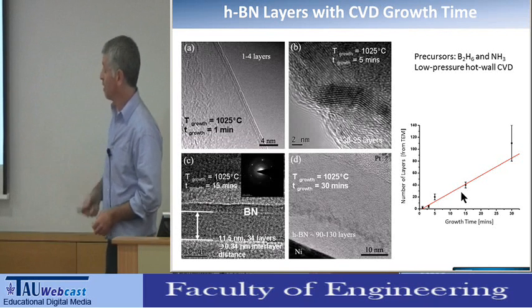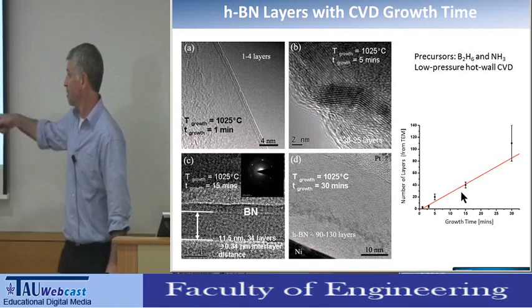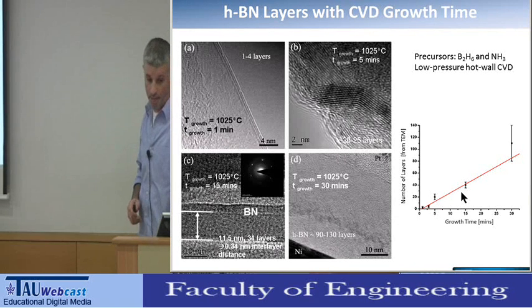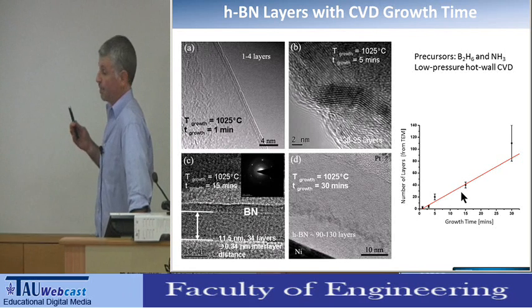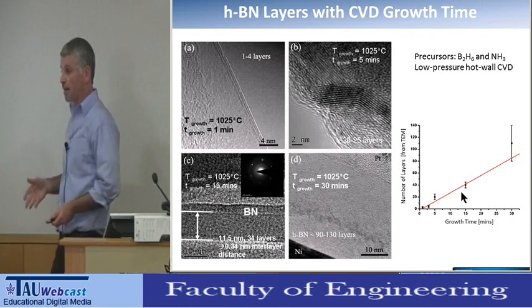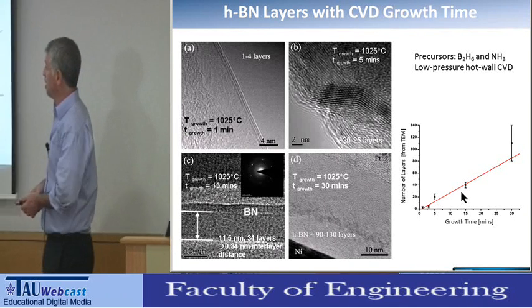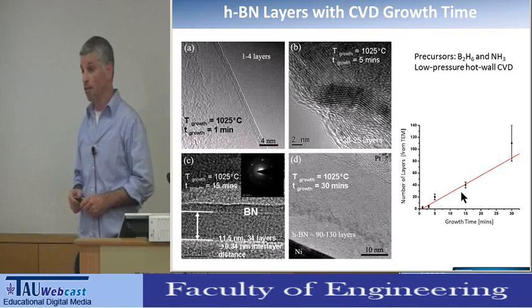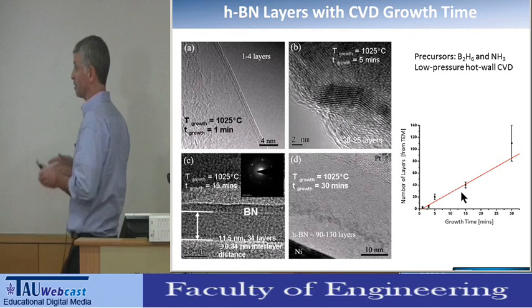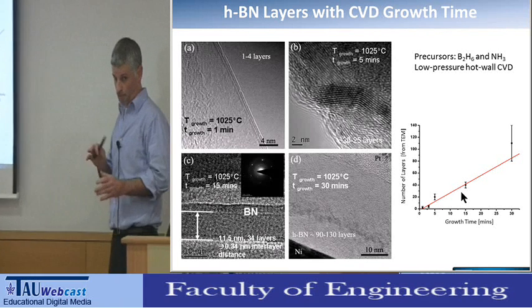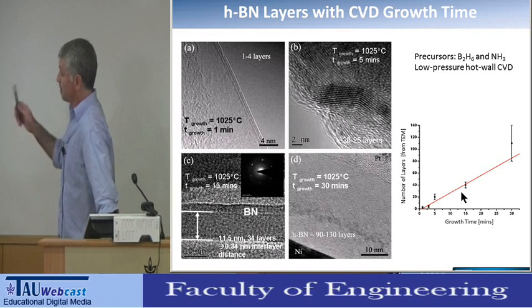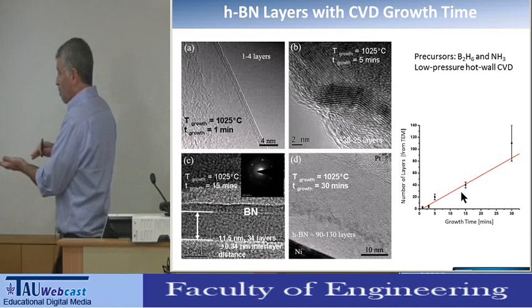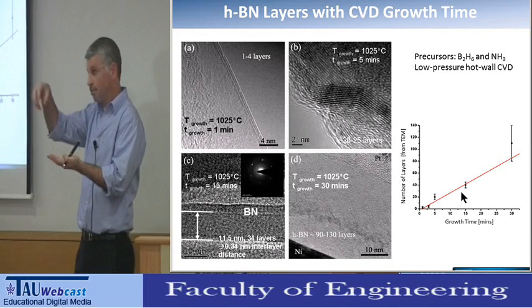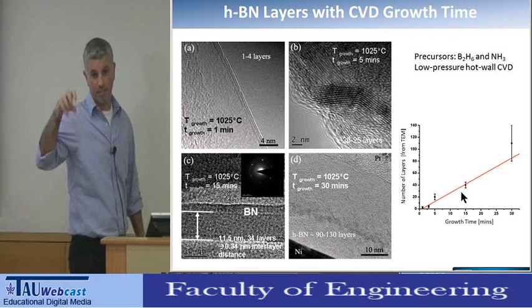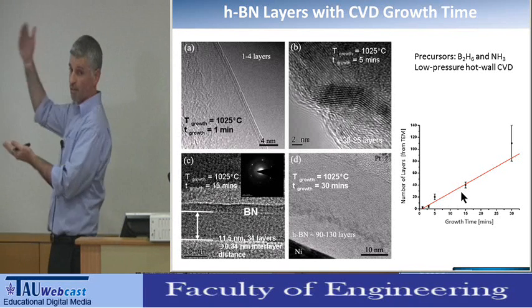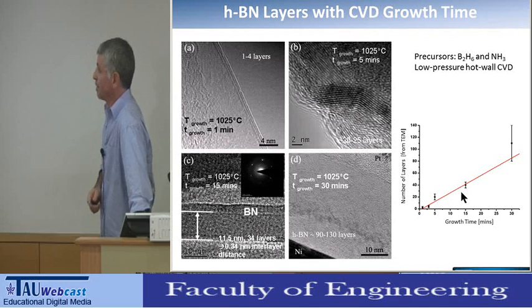we can grow from only few layers to achieve, at longer times, more than 100 layers is not clear yet. And one of the reasons for that could be that the mechanism of growth is by diffusion into the bulk and segregation out, similar to the case of few layers graphene and nickel. But we thought at this time that this is not possible because the solubility of boron, and especially of nitrogen, into nickel, it should be very low. Today, actually, we are changing our opinion about that, and we are still studying that. Another reason could be that somehow the boron and nitrogen species just attach to the edges of the already formed HBN or to defects in the film, thus promoting the growth of additional layers. So we don't know yet what is exactly the mechanism for that.